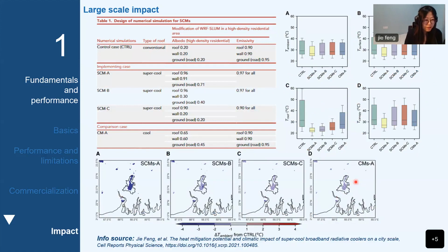If supercool roofs have been applied at a large scale, what will happen? In our research last year, three supercool materials, you can see A, B, C here, were applied to the entire city of Kolkata, an Indian city, using the weather research forecasting model. The simulated results show that the maximum reduction of peak ambient temperature can be up to 5.3 degrees. That is because the application of supercool materials reduces the peak ambient temperature of the entire city.